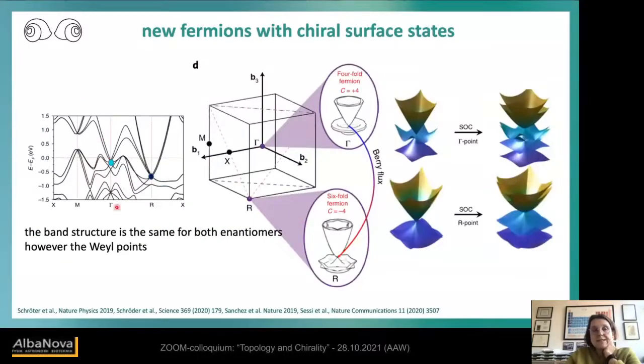So in the real system, here in the B20 structure, we have a 6-fold degenerate point. So we have 2 points here, a 6-fold and a 4-fold degenerate point. At the gamma point, we have a 4-fold degenerate point. At the R point, we have a 6-fold degenerate point. You see there are different energies. They even have different degeneration, but they are also a pair. And here you see what happens if you apply spin-orbit coupling, you get the splitting, and spin-orbit coupling therefore plays also a role.